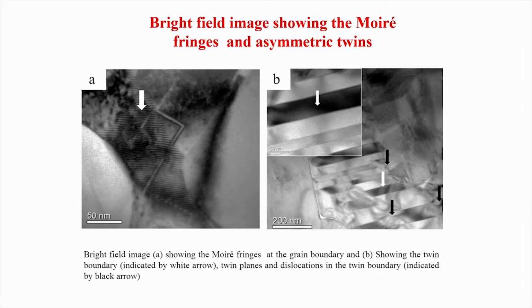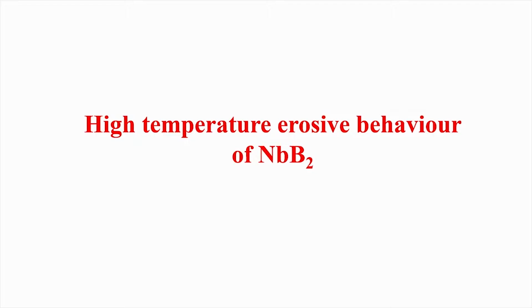These asymmetric twins essentially indicate that when these materials are heated at high temperature under uniaxial compaction, deformation twins are also generated, particularly at high temperature and when it is cooled down. So, these twins are present across the grains, which is the way it should be, because once a twin starts, it should not terminate in the middle of the grain unless it is intersected by another advancing twin. That is what we learned in the standard materials science textbook, and we also observed the same phenomenon in the case of ceramics. Now, coming to the high temperature erosion behavior.